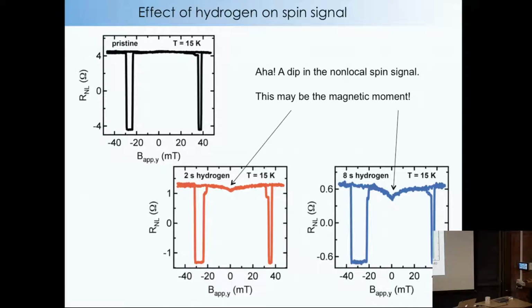And then we look at the spin signal, and this is basically the signal that I want to understand or explain. This is a spin valve signal. It looks like the typical spin valve signal. But when you start putting hydrogen on, you start noticing there's a dip as a function of magnetic field. And if you put more hydrogen on, the dip is relatively larger. The way that I interpret this is that at low fields, the magnetic moment from the hydrogen is interacting with these spin polarized electrons and depolarizing them. But when you apply an external field, you start decoupling in some way the electron spin from the magnetic moment, and so you start recovering the higher spin polarization at the detector.